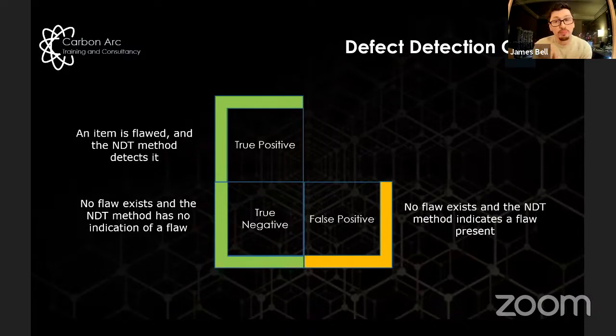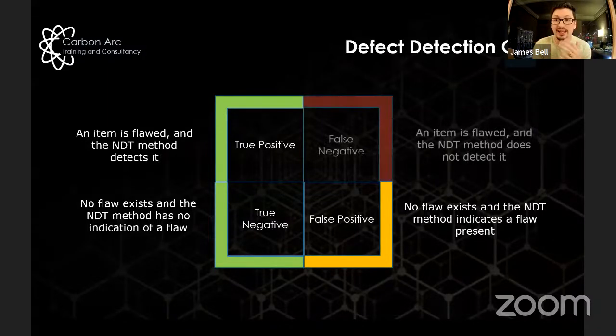We then move into false positives. So I call this a yellow zone because here there's no flaw in the component, but the NDT says there is. Now, the reason why I'm saying this is like a yellow, orange, amber type area is that in umbilicals, there's a good saying, which is, if in doubt, cut it out. So we don't say, oh, can we live with it? Just put it in the water, it'll be fine. If there's any sort of reason, we chop the weld and re-weld it. So a false positive is not good, but it's better than the last one, which would be a false negative. That's where there is a defect and our NDT method doesn't detect it.